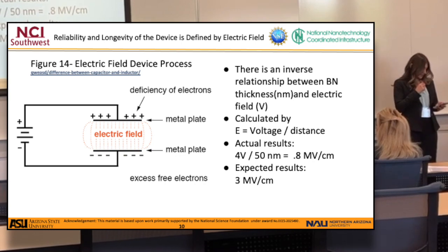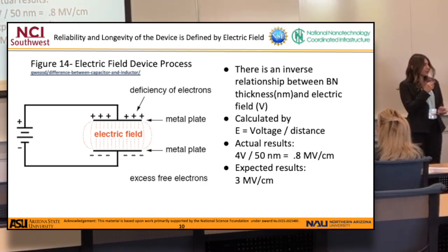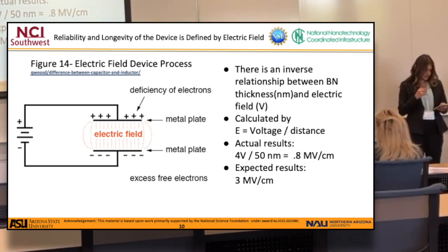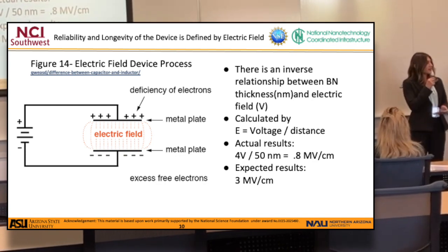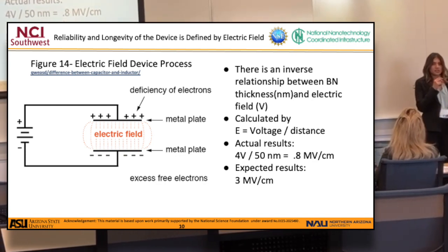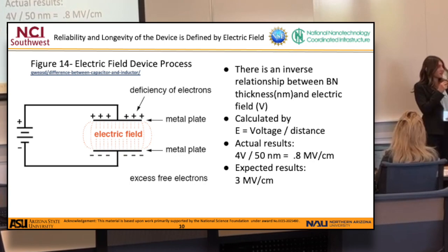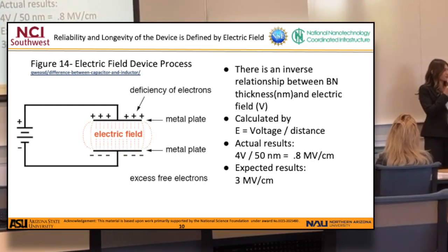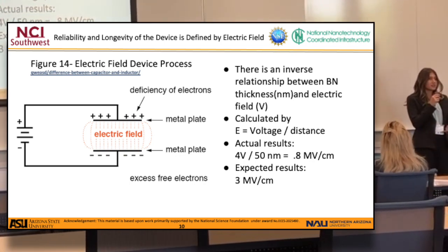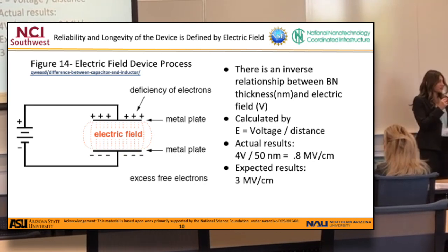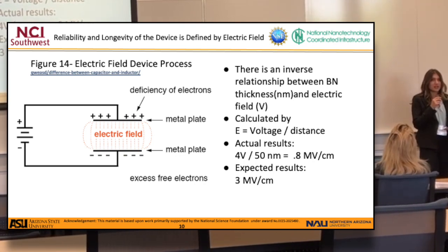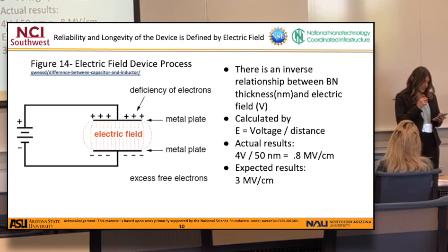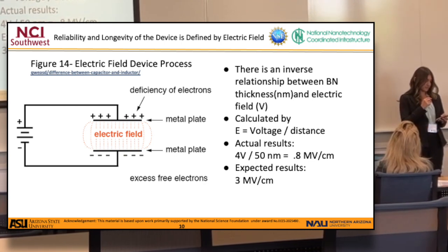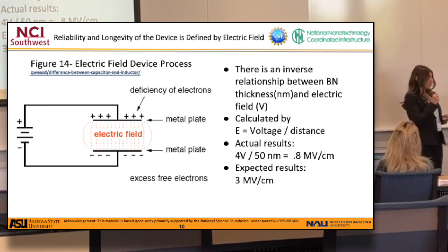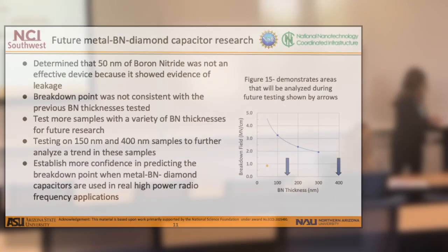So we are expecting an inverse relationship between boron nitride thickness and electric field, and this can be calculated by voltage over distance. During actual testing, we experienced that the electric field was 0.8 megavolts per centimeter, but we expected that it would be 3 megavolts per centimeter, and this, once again, can be explained by the leakage that we discussed previously.